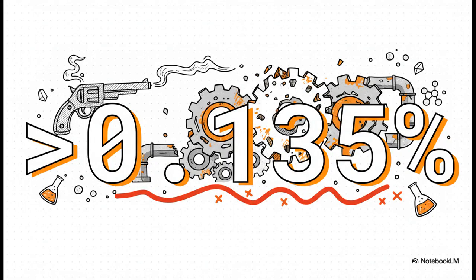And here it is, the smoking gun. The research pinpointed a precise tipping point. Once that sodium oxide impurity in the salt gets above 0.135%, the corrosion goes from manageable to completely unacceptable. That is the line in the sand you just can't cross.